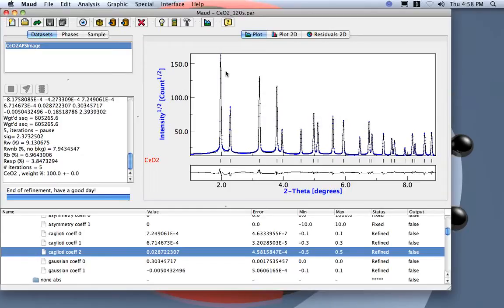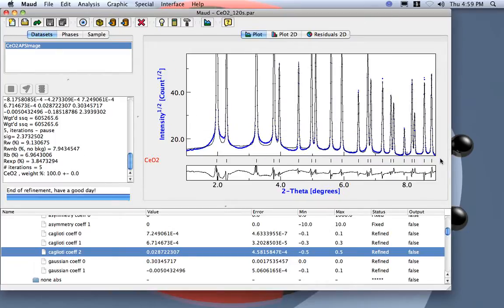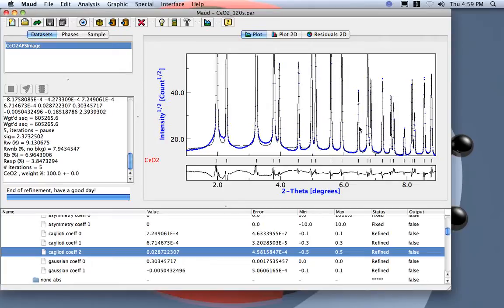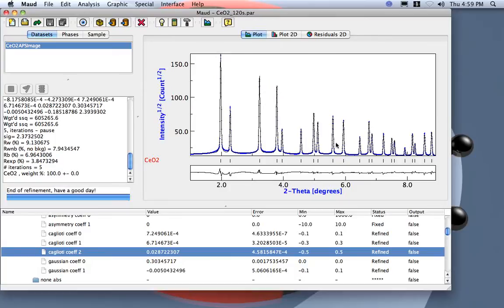If you want to do it better, there are some things we can check. If we check the lower part here, you see there is one part we will never get correctly with a profile function like this one. I know that this is due to the fraction of the cerium oxide with nanoparticles. There is a small fraction inside that is causing this bump over here, and I want to separate that one from the rest. This is a good example of how to do it if you have a powder with two components inside.